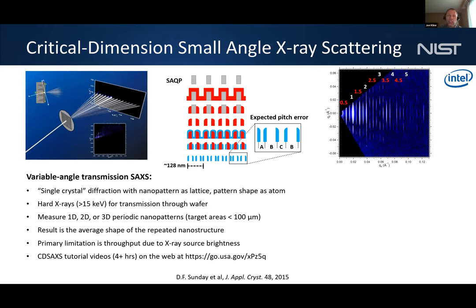And so the example that you have on the left there, that video is essentially one of these samples. And so this is a composite scattering pattern that you get. This is where you combine the different angles that you have onto a QX, QZ map. Since it's not coherent scattering, you can't directly convert this into a shape. So we have to do an inverse iterative method where you create trial solutions for what the shape is and then cycle through a couple million different guesses until you get something that matches.